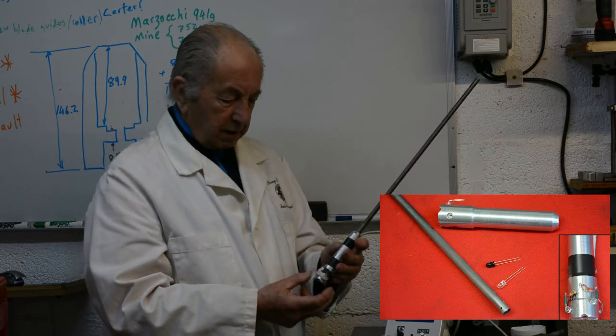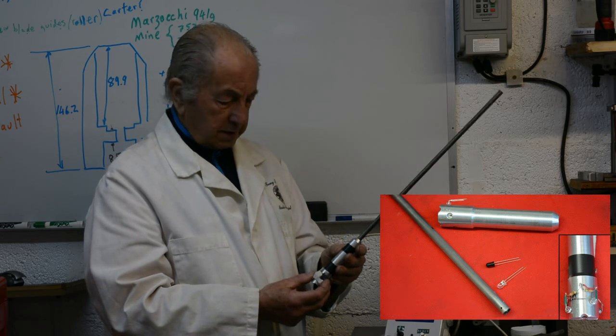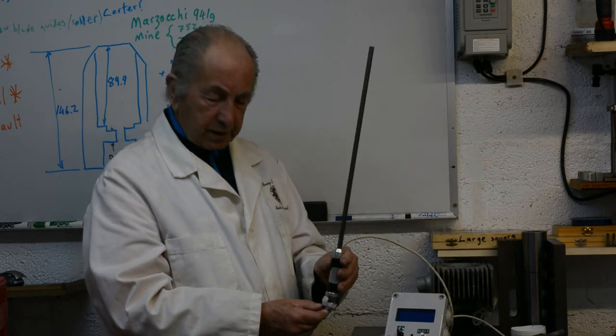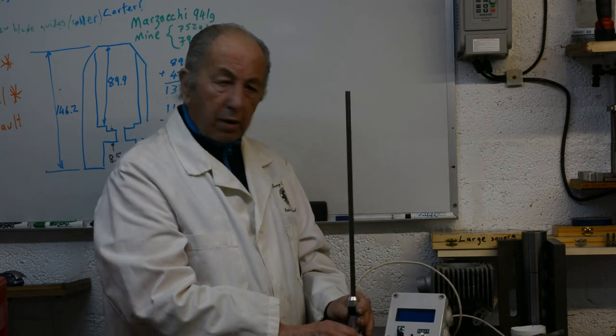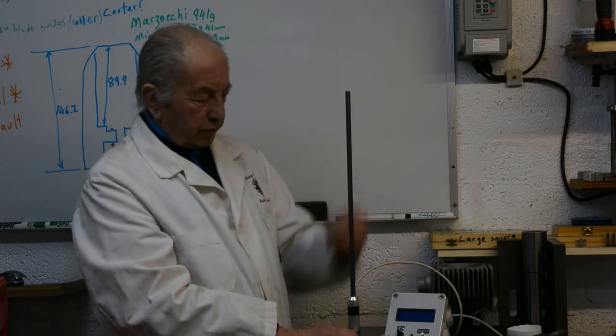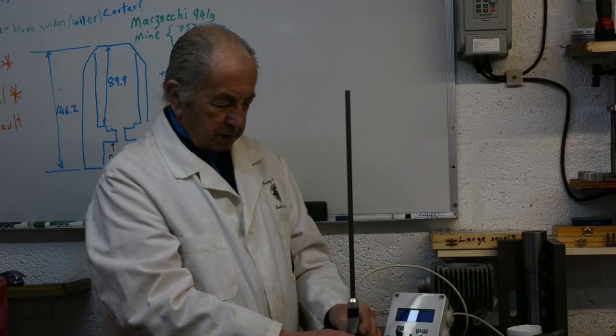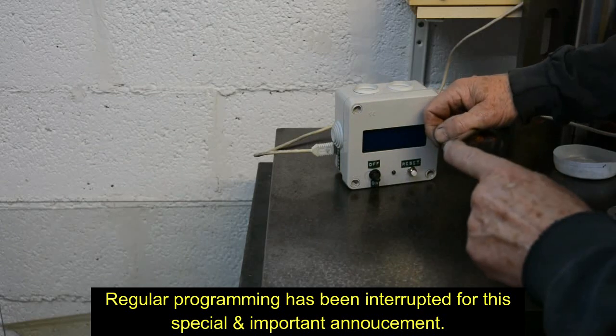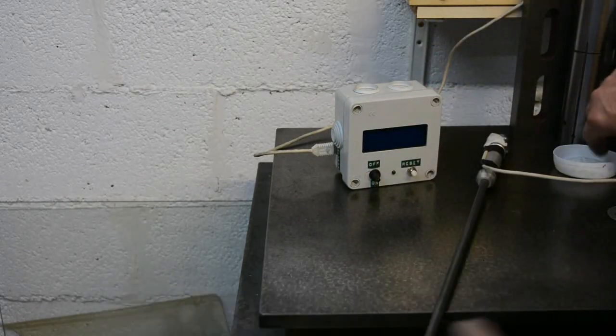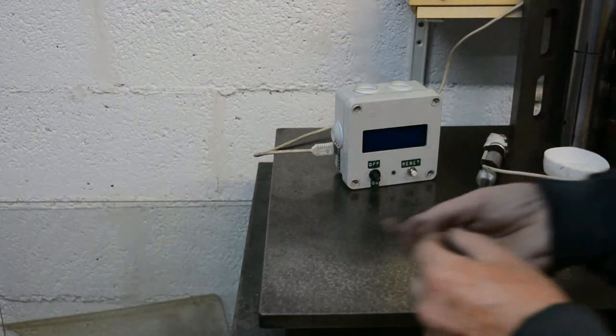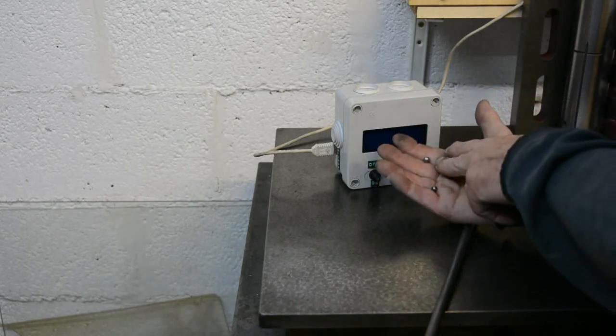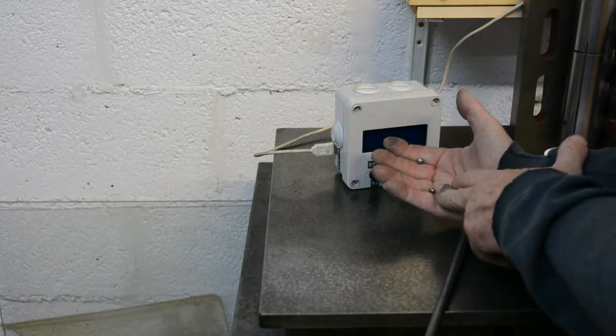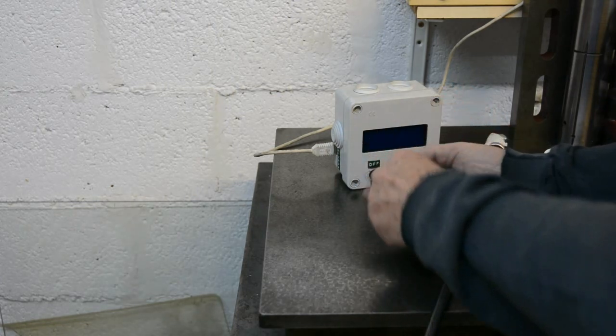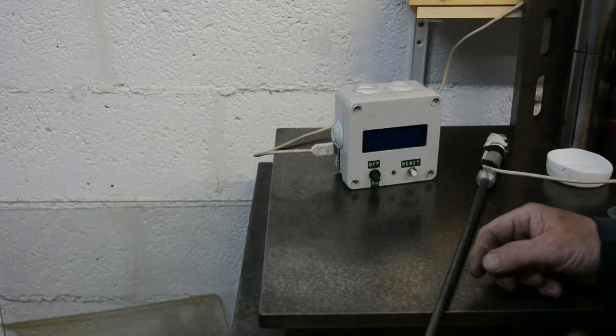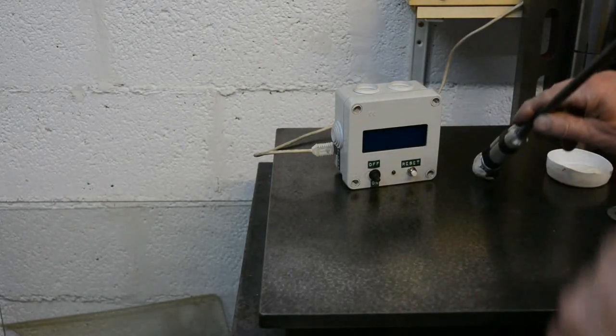It gives me a support for 2 infrared diodes and 2 infrared transistors, which are used to measure the velocity 7 millimeters above the contact position, because that will then allow the ball to sit down without interfering with the sensing. Now the internal diameter of this tube is 8 millimeters, and I've got 2 sizes of ball. The larger one up here is 7 millimeters, and the smaller one down here is 1/4 of an inch, which is 6.35 millimeters. So they're both quite loose in the tube, and they give absolutely identical readings. It doesn't matter which one I use.